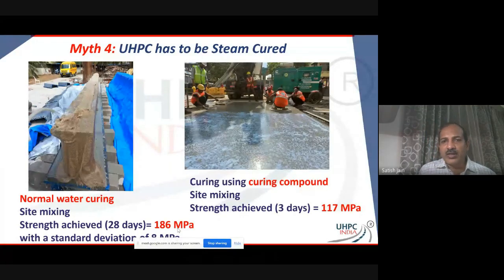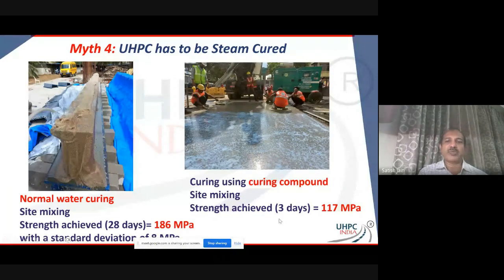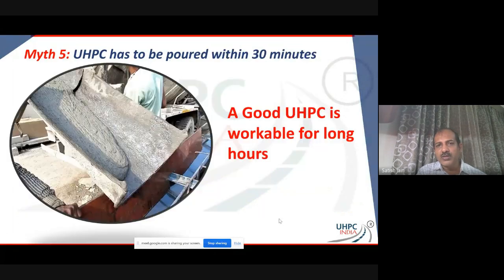And the right side material was used for a little bit of an overlay near a station in Mumbai. Again, 3-day strength achieved was about 117 MPa on this particular project. So you can make UHPC. Another myth is that you have to pour UHPC within 10 minutes, 20 minutes, 30 minutes. No. You can devise your own UHPC. You can have it workable for a long time.